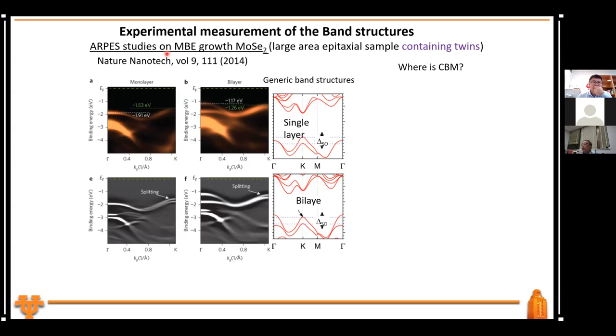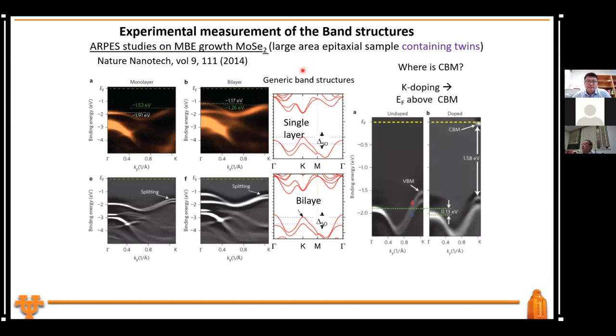So this group is Zhi-Xun Shen's group at Stanford, and they used the typical trick that almost every ARPES group uses: let's dope it with some alkali metal. After you dope it, you can move the Fermi energy to the conduction band minimum. But you can dope it just right above it, because you cannot dope much more than that, right?